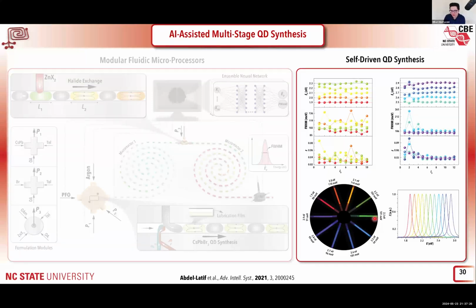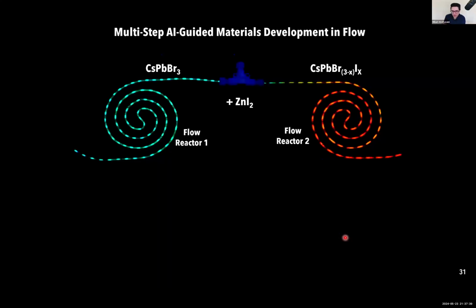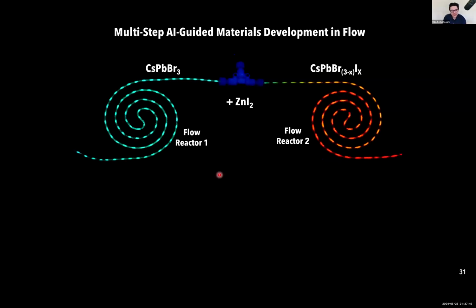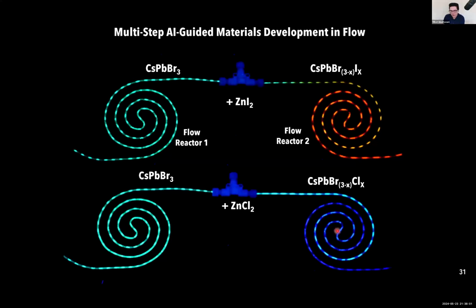These are some examples of those autonomously synthesized quantum dots. These are metal halide perovskites, cesium lead bromide, chloride, iodide, or mixed halides with different target peak emission energy or emission color. Here's a video of real-time operation of the flow reactor here under UV. That's why you can see the color of these quantum dots. And the first reactor is synthesizing green emitting quantum dots. The second one is doing a band gap tuning, halide exchange reaction. Now, depending on how much halide salt and what ligand you use, you can tune the target optical properties of these nanocrystals. You can go from green to red or green to blue.